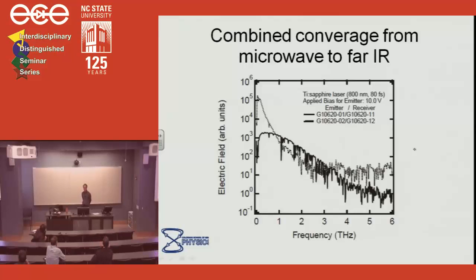For the terahertz devices, was that generated from an FFT? These aren't sweepable sources. The way you do the sweeping on these things is mechanically by moving one of the stages. You have a delay line. So basically what you're doing is you're taking the correlation of the transmitted and the received signal, and you're sweeping one of those by moving a delay line. So you can get incredibly high temporal resolution because stages are so good now, linear stages.